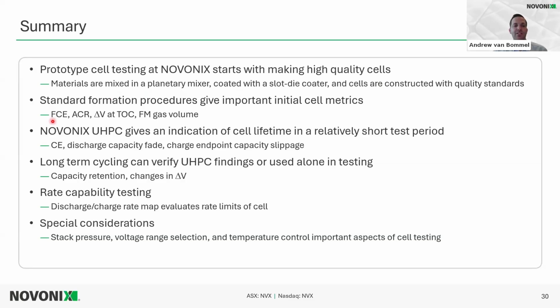One is the first cycle efficiency. Another is ACR. That voltage drop at top of charge is a really important metric, as can be the formation gas volume. And these are especially important when comparing different electrolyte systems. Using NOVONIX UHPC gives an indication of cell lifetime in a relatively short period of time. If we look at the discharge capacity fade, we can quickly predict what the discharge capacity fade will look like during cycling. And then the charge endpoint capacity slippage is a great metric to see comparisons and to understand when that cell would experience rollover.